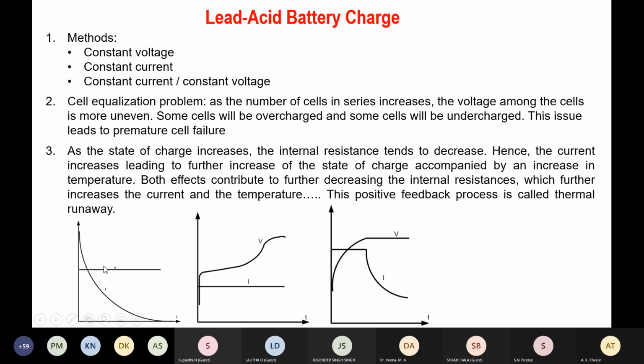However, constant current and constant voltage charge is also used for lead acid, but these two options may not be suitable for energy storage and charging of a lithium ion battery. The reason is very simple. With constant current charging, voltage is achieved very fast, but net energy at the desired designed level may not be achieved, because a large number of ions need to be pushed back from cathode towards anode end.